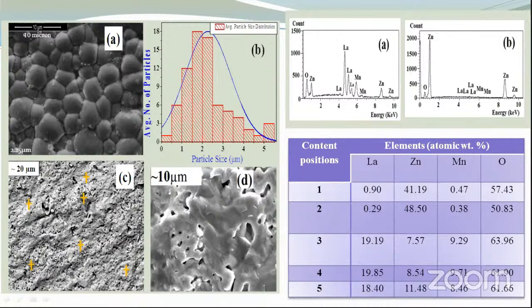So these are the back scattered compositions of this SEM. The back scattered image of the same material is shown in this figure, figure D. This shows the agglomerated grains and some porosity, at higher magnification than figure C. So this is the composition. EDS spectra also support our measurement. This whitest area is the major phase of this material, which has the composition of all the constituents of the present material, and these defects or dark regions indicate the minor phase, which shows a lack of lanthanum. Lanthanum concentration is lacking in this dark region, in the minor phase regions. So this composition in atomic weight percent is shown in this table.